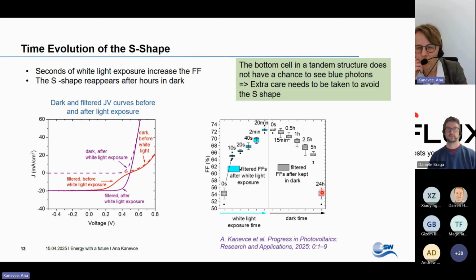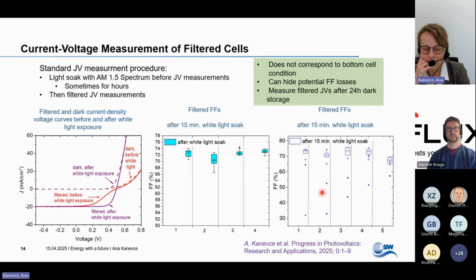This brings me to a point of how we measure JV curves. Standard measurement condition in our lab and in other labs is to do a white light soak of solar cells before we do JV measurements. This is okay, this improves VOC, this improves fill factor, it's fine. However, this doesn't correspond to a bottom cell condition.